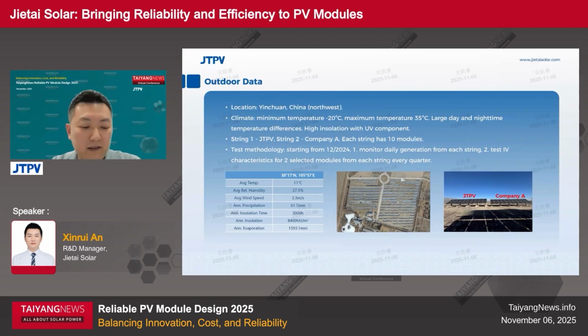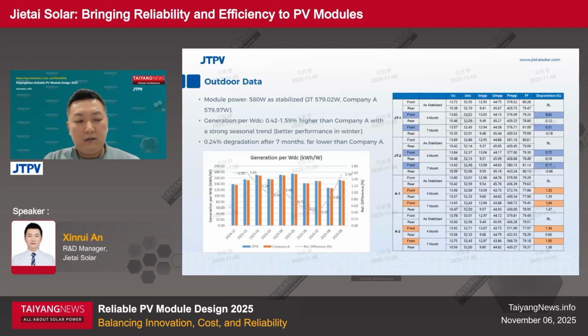So starting from last December, we've been monitoring daily electricity generation and testing the IV characteristics of the same two modules from each string every 3 months to monitor degradation. All the modules are pre-stabilized with an initial power around 580 watts. After 10 months of operation, we can see that our group has slightly higher generation per watt over company A, and the gap is between 0.4% and 1.6%, with a strong seasonal trend.